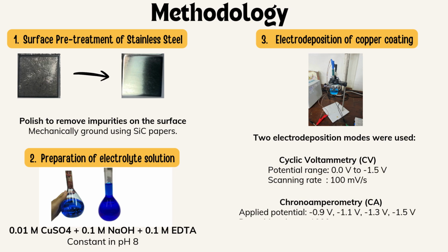Moving on is the methodology that was used in this study. Firstly, surface treatment of stainless steel by polishing mechanically using silicon carbide papers to remove any impurities and then sonicated with acetone to clean it thoroughly. Secondly is preparation of electrolyte solution by adding copper sulfate, sodium hydroxide, and EDTA with constant pH 8.